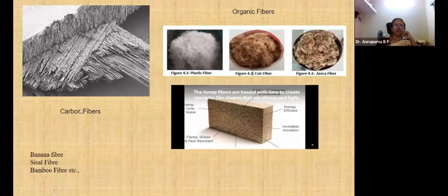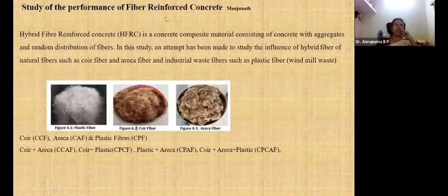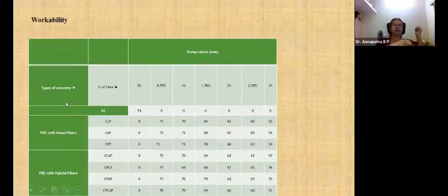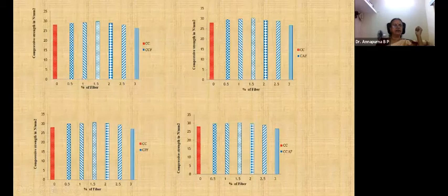And here, the fiber reinforced concrete. There is a study being done on fiber reinforced concrete using plastic, coir, and areca. These are the plastic fibers which we have extracted from windmill waste, from the production of wind blades. This is the coir fiber and this is the areca fiber. The areca fibers and the plastic fibers are treated and used here. They are treated with sodium hydroxide and then used. The treated fibers will be better than the untreated fibers. I'll just go through this quickly.